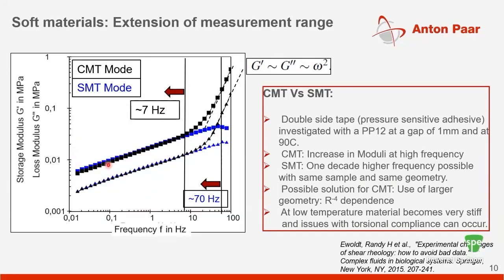Here I am showing you some data of a frequency sweep measurement on a PSA type—a double-sided tape, which was investigated with a parallel plate type geometry. This was done on the multi-drive device, where you can see data from both the CMT and SMT mode, which we talked about earlier.